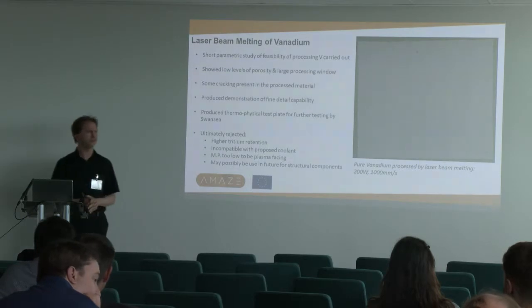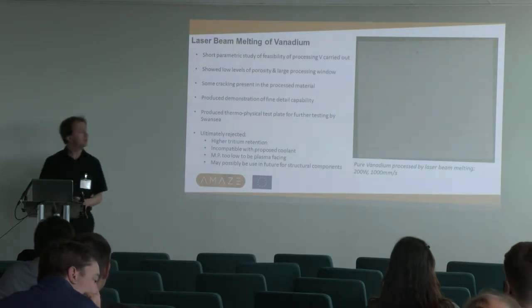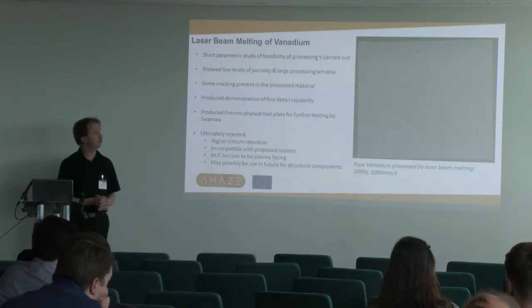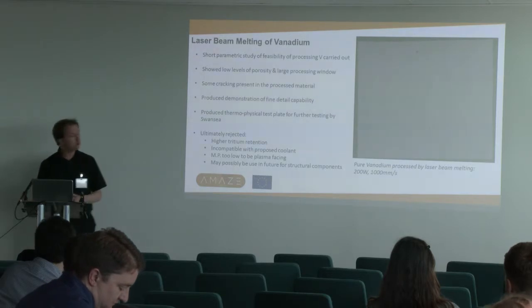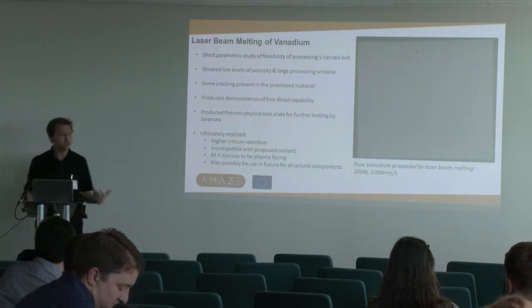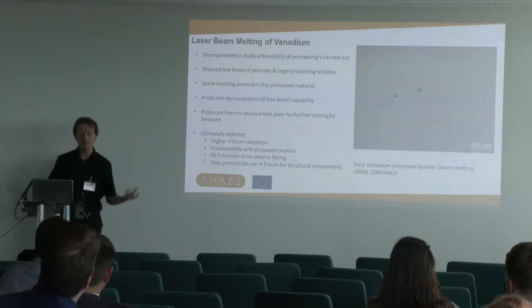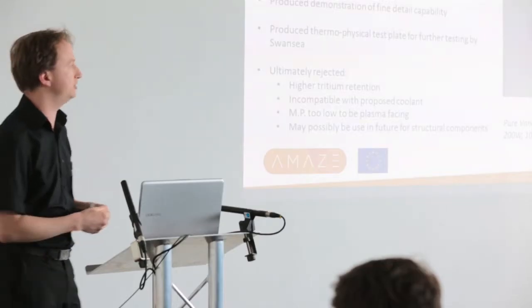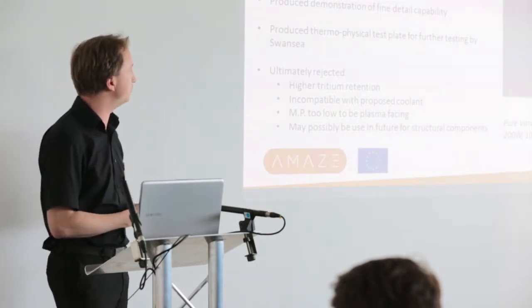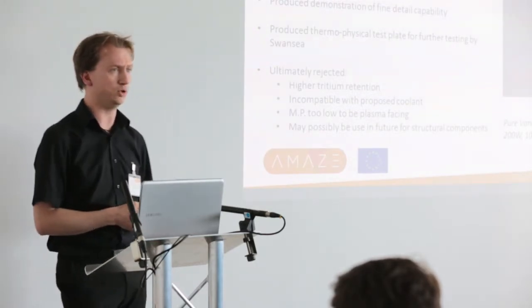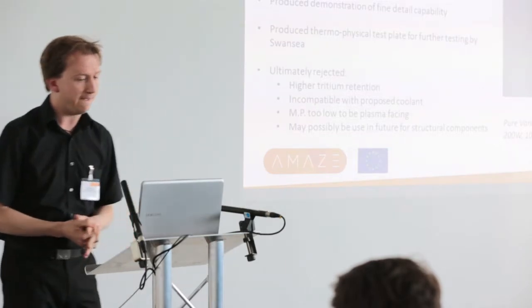So I'm going to start off with the work we carried out on vanadium. This was some time ago at Birmingham. It was basically a pretty quick parametric study, just looking at the feasibility of using vanadium. It showed relatively low porosity throughout a large processing window. There is some grain-bounded cracking present in the material. The refractories are notoriously brittle at room temperature and susceptible to oxygen pickup and oxygen embrittlement.